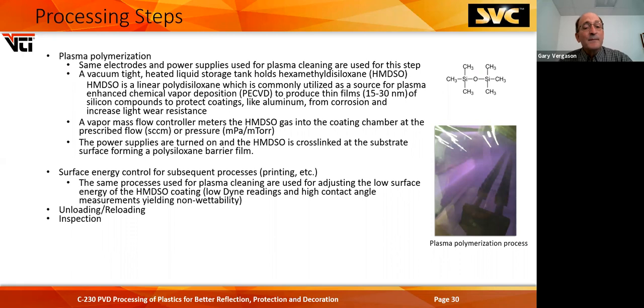In the plasma polymerization step, the same electrodes and power supplies are used that we use for plasma cleaning. You've got a vacuum tight storage tank of the material that holds the HMDSO, at only a slightly elevated temperature. This material is very volatile, so you don't want to overheat it. It's a linear polysiloxane. The PECVD film that we need for corrosion protection on aluminum is only 15 to 30 nanometers thick.